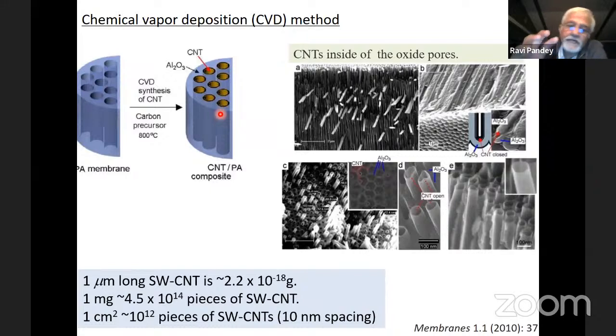Now I would like to make a point about a 1 micron long single walled carbon nanotube. The mass, or the weight, is about 10 power minus 18 gram. So if we talk about 1 milligram of carbon nanotube, we have really 10 power 14 pieces of these carbon nanotubes. So you have to think about a very, very small quantity. It means we have a large number of these carbon nanotube bundles in the system.